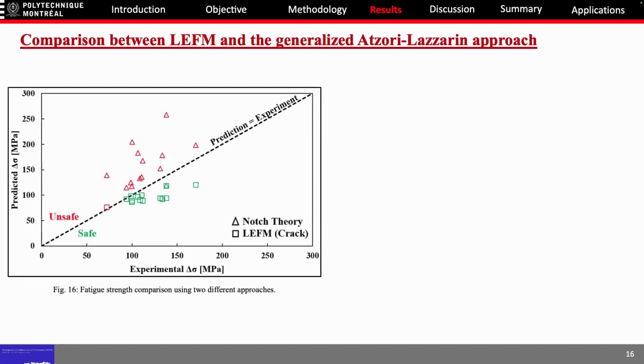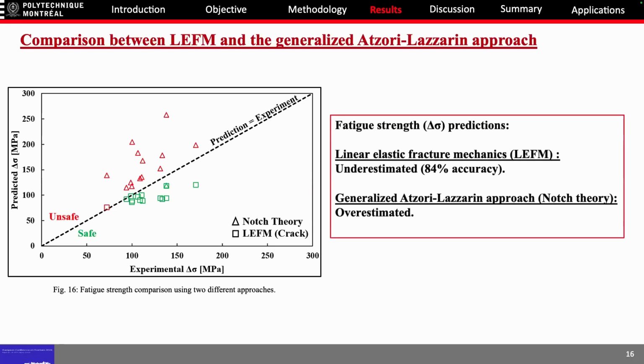So I did a comparison between LEFM and the notch theory on this graph. On the y-axis is the prediction of fatigue strength. The x-axis represents the experimental fatigue strength, and the black dashed line represents where the prediction equals the experiment, so basically the ideal prediction model. The triangles, mostly red, represent the notch theory, which is unsafe because it overestimates the experimental test. The prediction is overestimated.